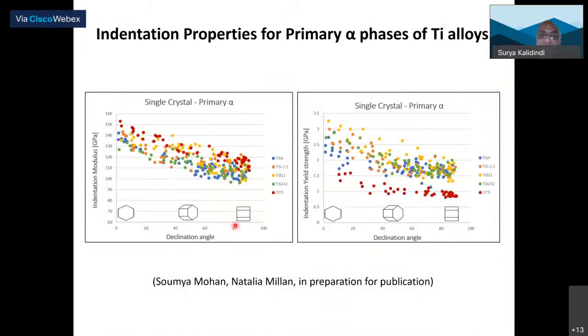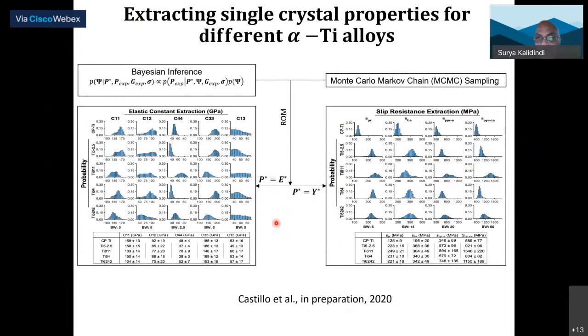Now, of course, the elastic constants are something everybody has, so they're not that interesting. The more interesting thing is if we can actually predict the CRSS values, critical resolved shear strength values, in hexagonal systems of different chemistries. Now we have different slip systems, pyramidal, basal, and all those things. So what can we do? What we are showing here is that by doing indentation on grains of different orientations, we are making estimates of the elastic constants in hexagonal metals, so a lot of different metals. And also CRSS values. So this is now the CRSS values for different metals. Obviously, some distributions are reasonably narrow. That means I'm pretty confident about some of these numbers. But some others are pretty broad.